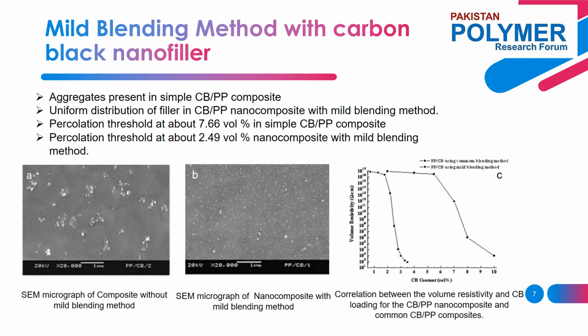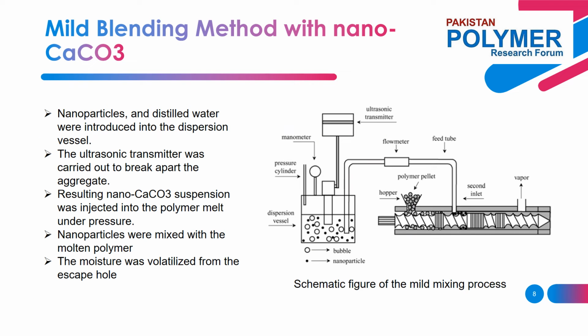When the carbon black content reached the percolation threshold, the effective tunneling zones of the nearest neighboring particles overlapped and tunneling conduction occurred. Overall, this research shows that nanocomposites can be fabricated successfully by compounding polypropylene with nano carbon black aqueous suspension using the mild blending method.